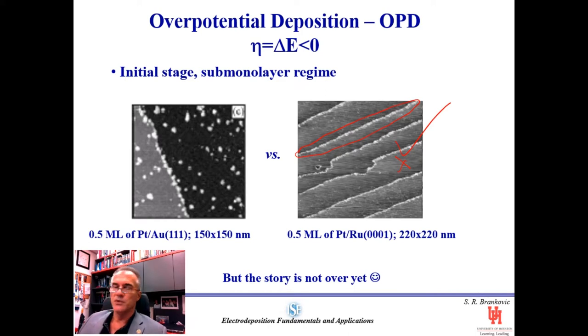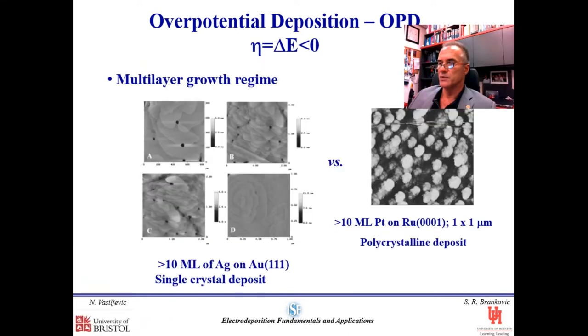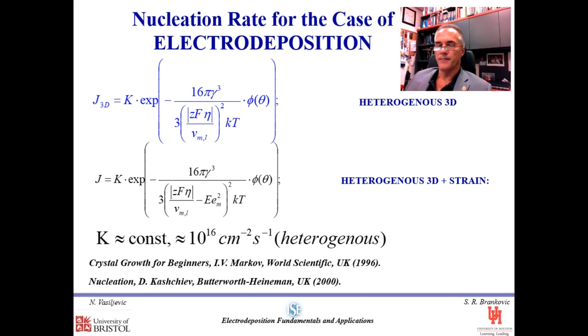To understand a little bit more about this, I would just point out that depending on how we do the process, we can have perfectly executed 2D growth, like here shown, silver on gold, but we can also have 3D growth, which is usually not the desired one, which is shown here, platinum on ruthenium. So obviously, overpotential is important in understanding the nucleation phenomenon.